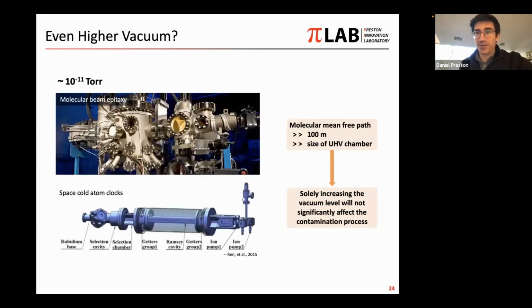Question might come up, well, what if the vacuum just wasn't a high enough level? What if we go to even higher vacuum or lower pressure, right? We were already at a value of pressure such that the mean free path was bigger than the size of the chamber. And so our guess is that just increasing the vacuum level will still have only ballistic transport and probably still have contamination of the surfaces in the same way that maybe just regular 10 to the minus 8th torr in the XPS chamber would have given us anyway.